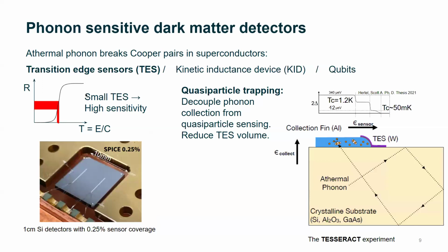For TESs, what is it? TES is transition edge sensors. Basically, we run a DC current through a small piece of superconductor. And through the Joule heating of the superconductor itself, it can hold its temperature at the critical temperature. And we cool the bath temperature far below the critical temperature. Then, because of the Joule heating, it just stabilizes itself on this transition edge. So it's called the transition edge sensor. And because of the sharpness of the resistance and temperature dependence, a small temperature change will transfer to a large resistance change. And if we use constant voltage bias, this resistance change translates to a current change and can be sensed by sensitive current sensors, for example, SQUIDs. So this is the basic idea.